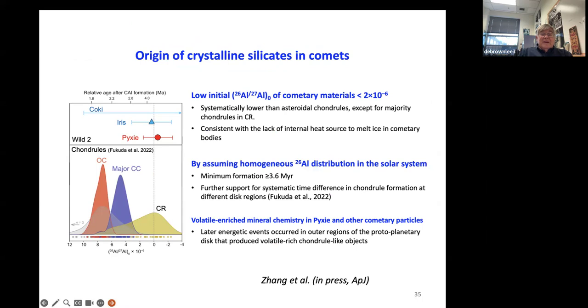And the origin of the silicates is very interesting. These are the upper limits obtained, implying the low initial 26-27 ratio of less than 2 times 10 to the minus 6, not 5 times 10 to the minus 5, but less than 2 times 10 to the minus 6. And if you assume a uniform aluminum-26 distribution in the early solar system, you can get an age. The minimum age is greater than 3.6 million years, which is very late.